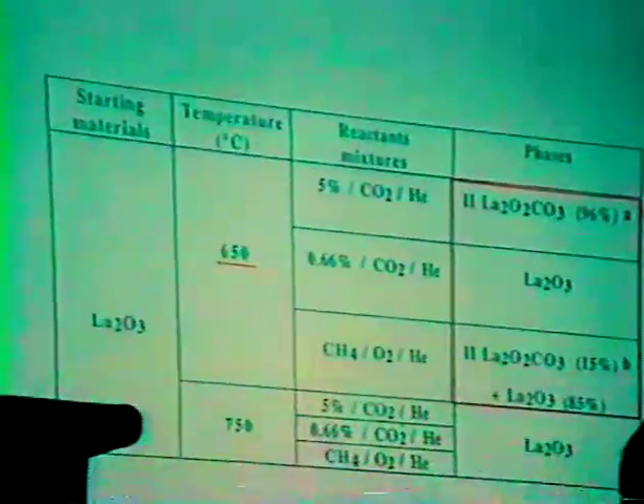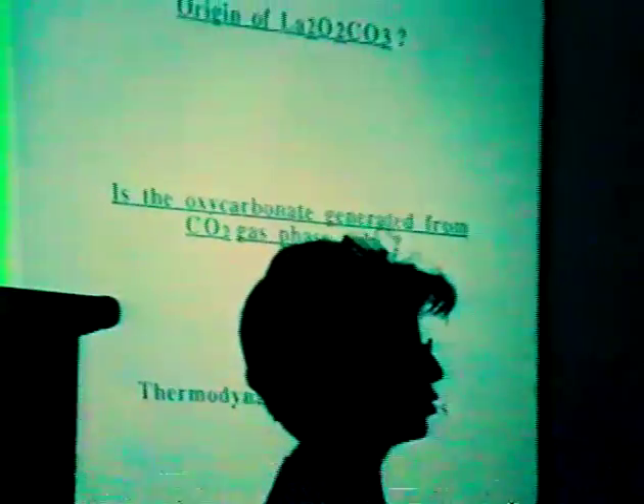By contrast, with the oxidative coupling of methane reaction, you convert 15% of the oxide to the oxycarbonate. And now the question is, what is the origin of this oxycarbonate which is observed during the reaction? In other words, is this oxycarbonate generated from the CO2 gas phase which is produced during the reaction?